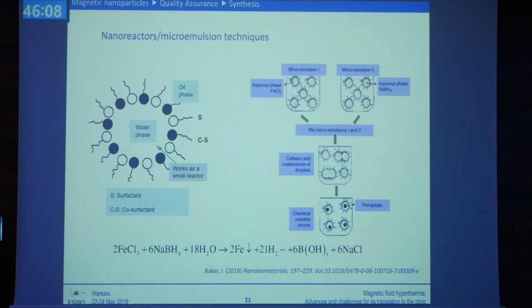For example, you see here this technique, which is called the nanoreactors microemulsions technique, where you can have two different inorganic compounds like ferric chloride and sodium borohydride, which come in microemulsions. And when you mix the microemulsions together, because of entropy, because of thermodynamics, because of the Gibbs energy, the microcells, the droplets, come together. As they come together, they create bigger droplets, and you have a mixture of these inorganic compounds, and in the end, you have the creation of iron. And this iron then can be oxidized, but it's already in a very small size.